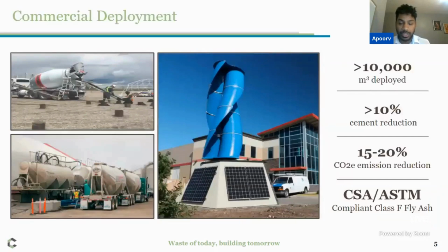And we've delivered over 10,000 cubic meters of concrete through Burnco and primarily Wholesome in the Western Canadian market thus far. What's exciting about this is both of them have been able to demonstrate that double-digit cement reductions are possible. And of course, none of that would be remotely possible to achieve in the field if we hadn't also shown that we were compliant with the relevant ASTM and CSA regulations as we've been able to demonstrate.